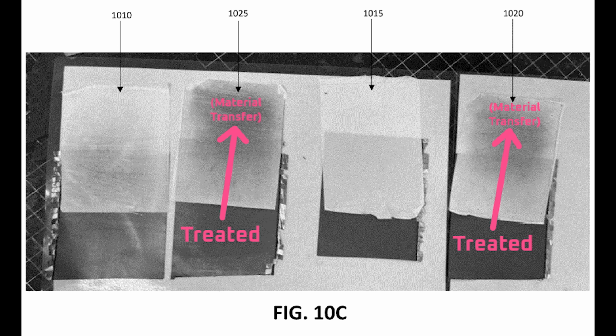Lastly, figure 10c shows that separators in contact with the plasma-treated electrode transferred a significant amount of material from the electrode when they were peeled apart, which indicates that the two components bonded. That's as opposed to the untreated electrode where very little material was transferred. This shows the glue-like effect of the plasma treatment that I mentioned earlier in the video, which should improve the structural integrity of the jelly roll. That, in turn, might have positive knock-on effects, like improving the cycle life of the battery cell by reducing the impact of expansion and contraction stresses as the cell is charged and discharged.